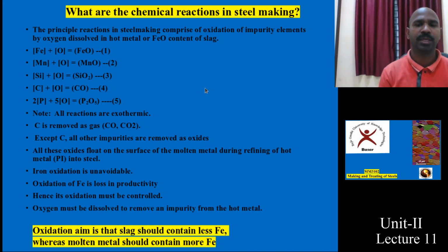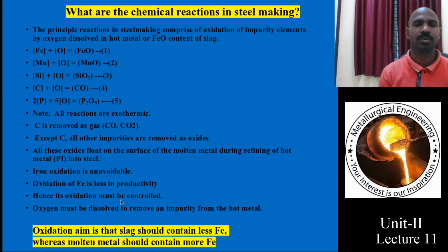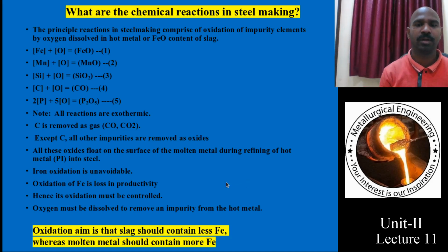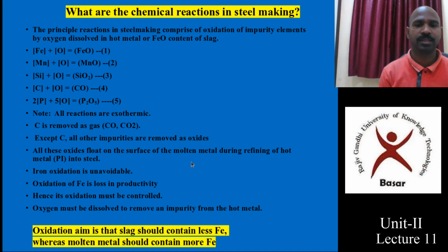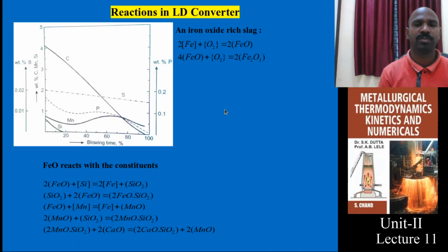All the oxygen dissolved in the steel can be removed in the consequent process called secondary steel making. The oxygen can be removed by using a suitable deoxidizing agent such as aluminium, which forms Al2O3 that solidifies as droplets and can be removed. Please make a note of that.